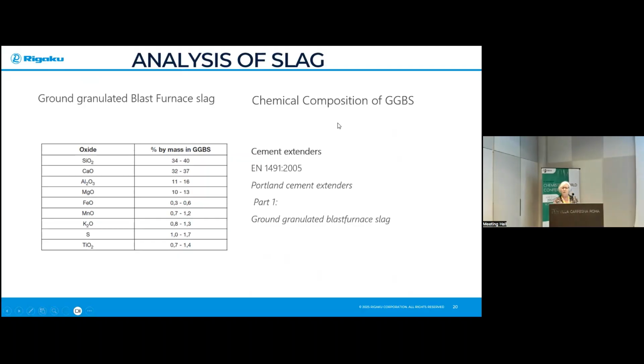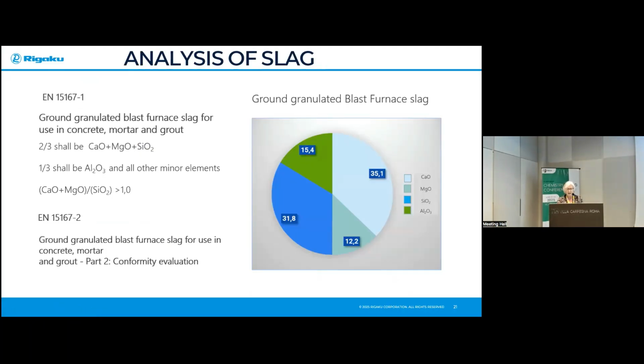Well, the chemical composition of ground granulated blast furnace slag is given here. So according to this international norm, we need to categorize and make sure the analysis of slag conforms to this composition that is stated in the international standard. So in the international standard, they say the ground granulated blast furnace slag to be used in concrete, mortar and grout should consist of at least 2/3 of calcium, magnesium, and silicon dioxide. And a third should be as alumina oxide and the other minor elements that could be present in that particular slag. And most importantly, the ratio of calcium and magnesium over the silica should be greater than 1.